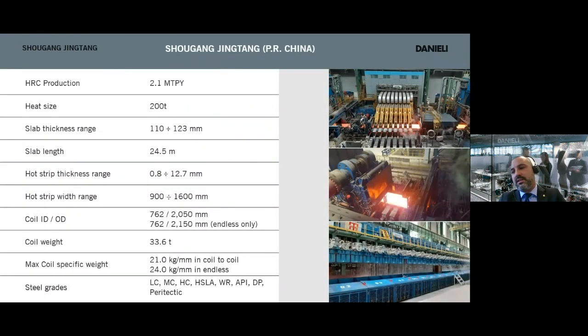The Danieli Universal Endless plant is a running plant. For over one year now, the Jingtang plant in China has been under production. Other references are ongoing or in the engineering stage. But now I just took the chance to share some of the achievements got at Shougang, which has a nominal production of 2.1 million tons, on the width range from 900 to 1600 millimeters, and the thickness range from 0.8 up to 12.7 millimeters.